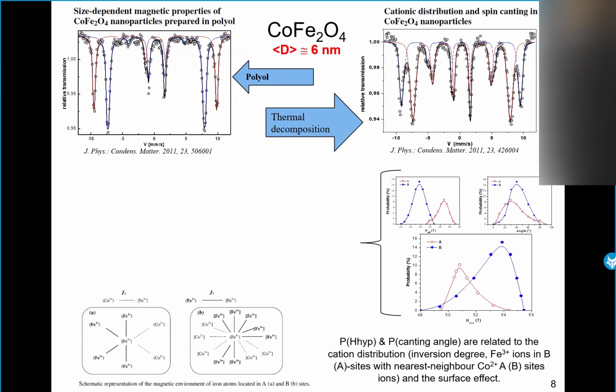By doing that, we obtain the distribution of the hyperfine field, and we do the correlation between the distribution of the hyperfine field and the spin canting, which are related to the cation distribution. So the position of the iron 3+ ion in B and A sites, with nearest neighbors of cobalt 2+ in A and B sites. That allows us to have a mean schematic representation of the magnetic environment of iron located in A and B.